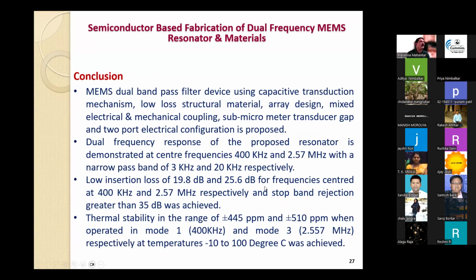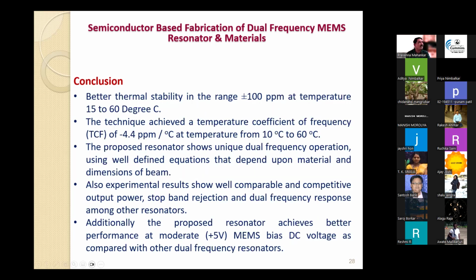the MEMS dual band, so we have two different bands at mode 1 and mode 3, was designed and fabricated using an electrical and mechanical coupling scheme with a 2-port electrical configuration and sub-micrometer transduction gap. The gap that I told you was 0.3 was the transduction gap. These are the results that we got at 400 kilohertz and 2.57 megahertz frequency. The thermal stability was 445 ppm and 510 ppm at mode 1 and mode 3 respectively. And these are all the different measurements that we have done.